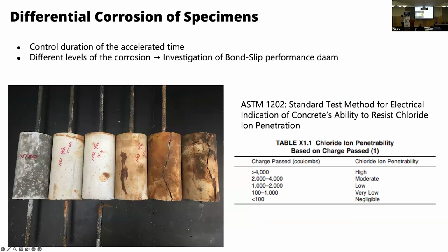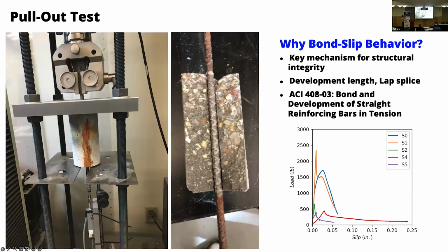So look at the beautiful corroded specimen over here. On the left, that is an intact specimen. On the right is the most corroded specimen over there. So by just changing the level of the corrosion, accelerating the level of the corrosion, we just made a specimen like this. And then we just pulled out the rebar to measure the bond strength of the structure. So that is actually the way that we just try to use.